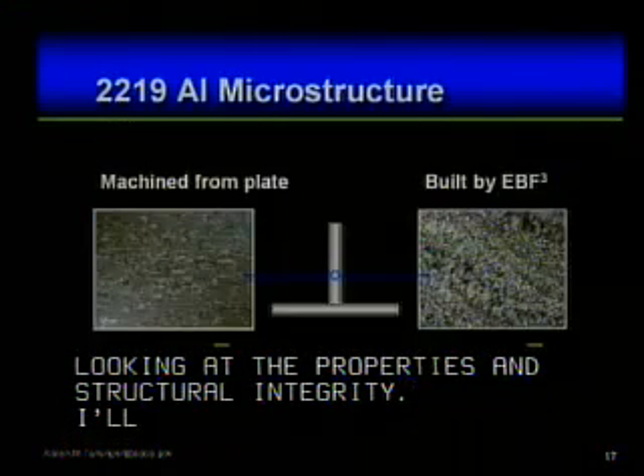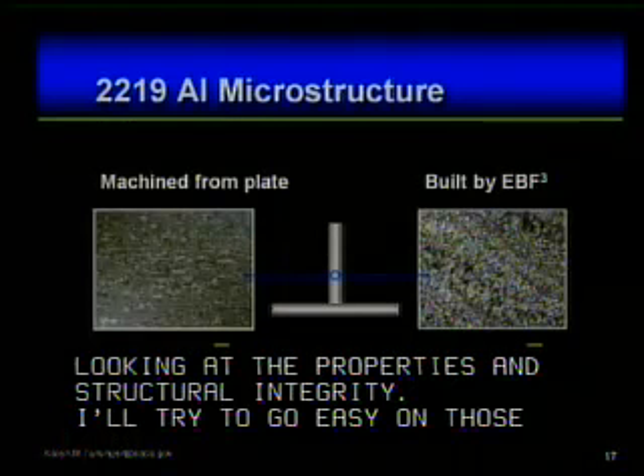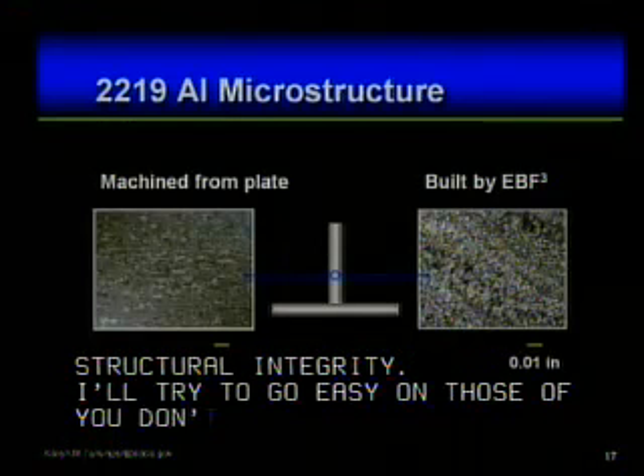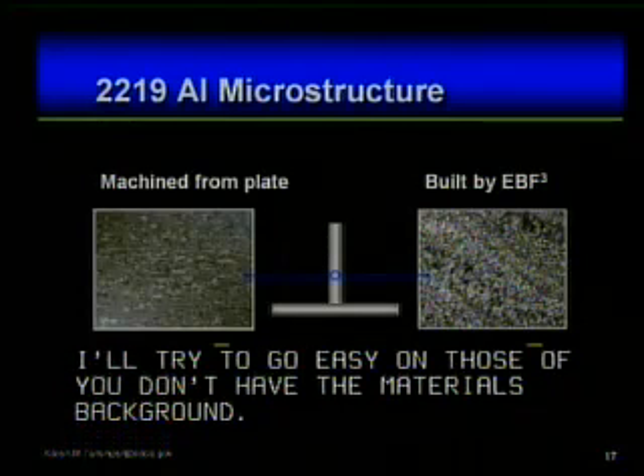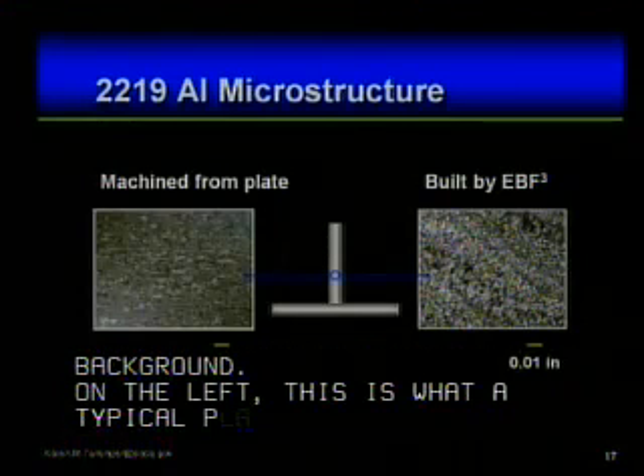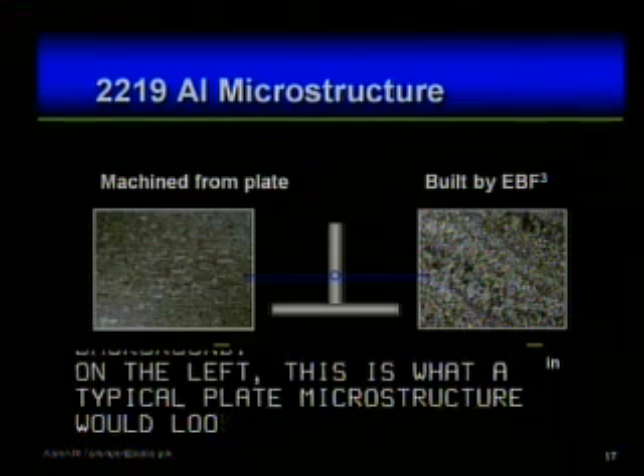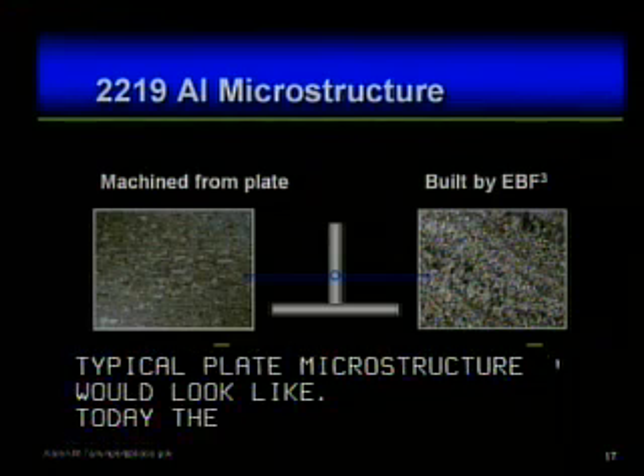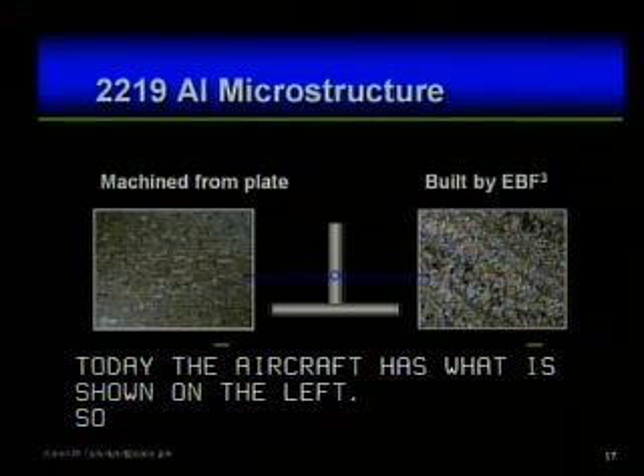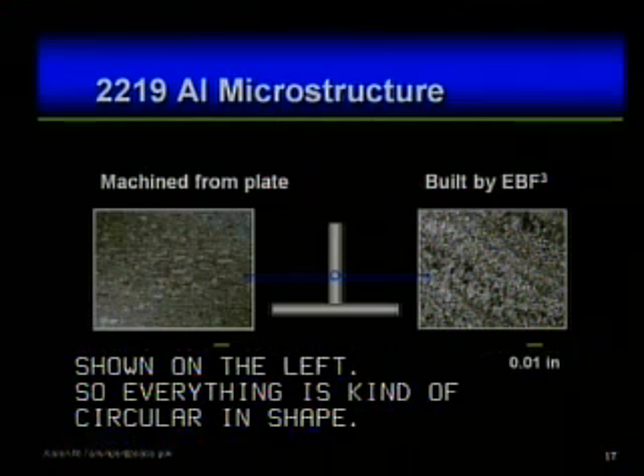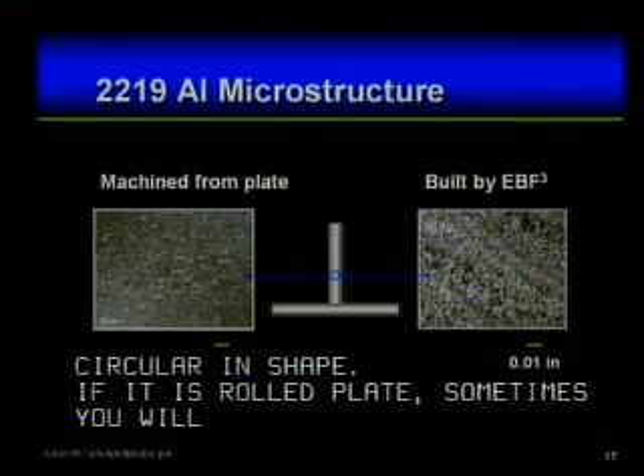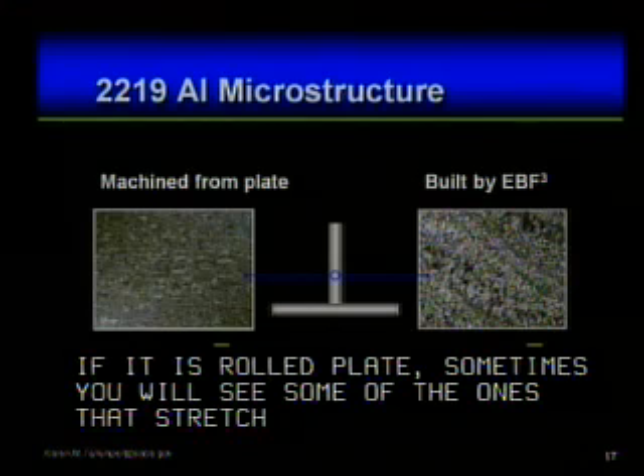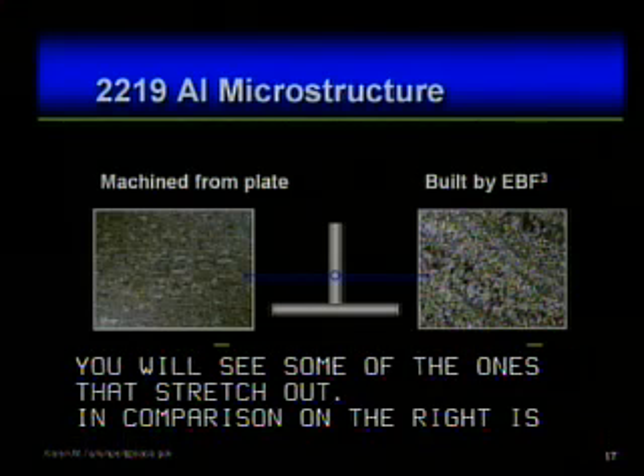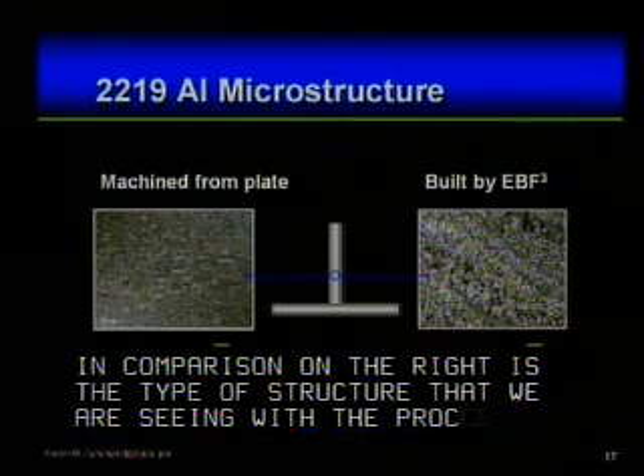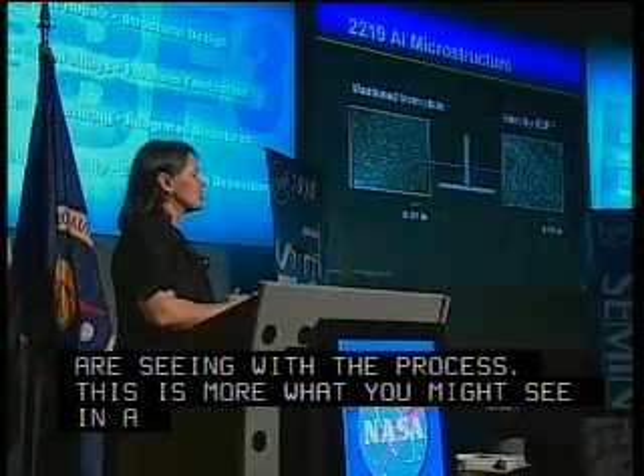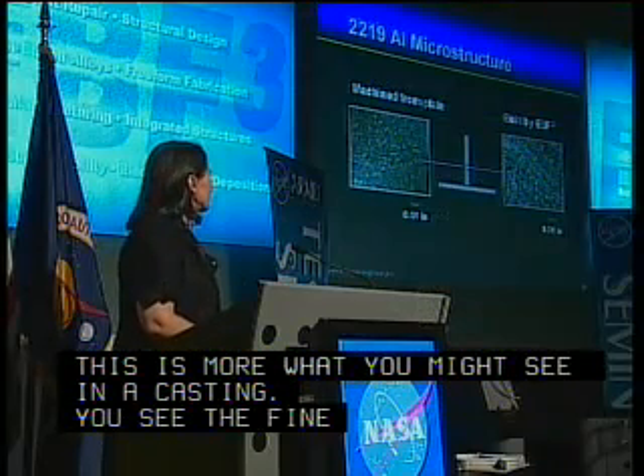Next slide, please. On the left, the picture that you see, this is what a typical plate microstructure would look like. And so today, the aircraft that are flying would have the kind of microstructure that's shown on the left. And it's kind of an equiaxed grain structure, so everything is kind of circular in shape. And if it's rolled plate, sometimes you'll see some of those grains that really stretch out. In comparison, on the right is the type of microstructure we're seeing with the EBF³ process. This is more what you might see in a casting. You see the fine grains and the large. There's a variation in the grain size, but it's still a relatively small grain structure.